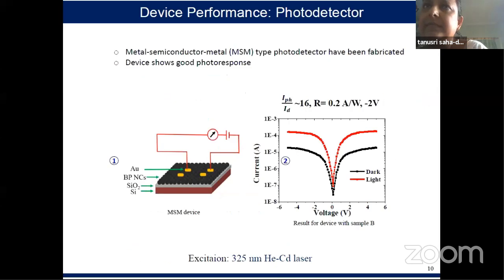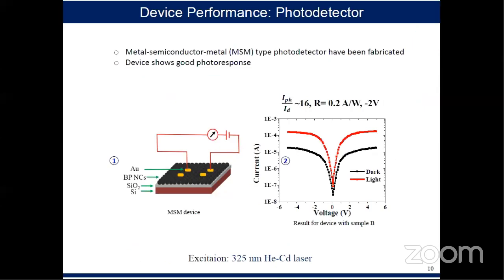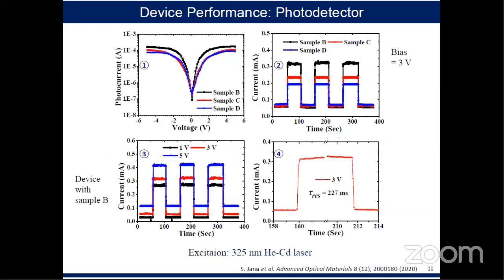Next slide. So then we have used these phosphorus nanocrystals to show the potential application. We have spin coated the sample over SiO2 substrate, and then gold top electrodes were taken by thermal evaporation technique. From figure 2, we can see that it has a moderate photo to dark current ratio of 16 and responsivity of 0.2 amperes per watt at -2 volt bias. While the excitation used was a 325 nanometer He-Cd laser.